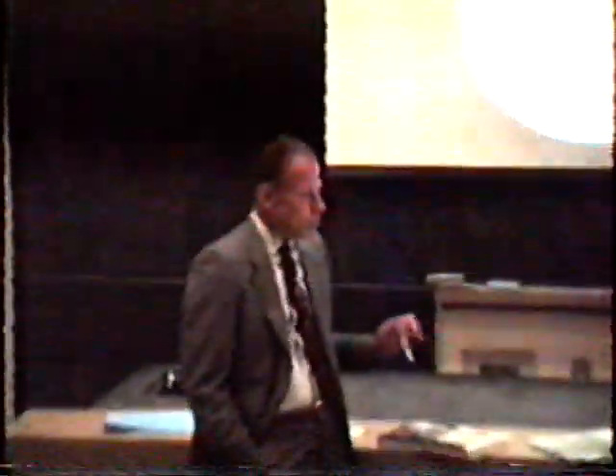This shows some of the calorimetric measurements during this experiment. One here, and this line here, is where you exactly break even, where the heat we're getting out is exactly equal to the heat coming in. We didn't start this until about the 12th day because we don't normally get excess heat until you run it for a while. And furthermore, we were working out problems with the possible leaks in the system. But you see on the 12th day, we were getting excess heat, at least in cell B. The dark line is cell B.